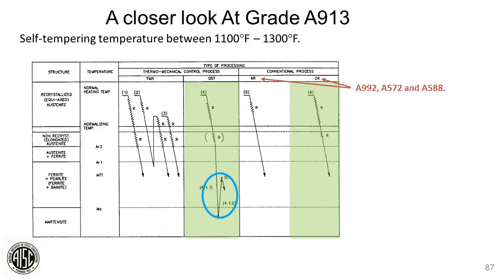If you can go to the next slide, we'll blow this graph up again. Here we go. This is the self-tempering temperature. In other words, we do all the control rolling, then the quench, that's this real steep line dropping down to below what we call the martensite start temperature. And then there's a self-tempering temperature. In order for the steel to be certified to A913, that self-tempering temperature, that rebound, has to be between 1100 and 1300 degrees. We go to the next slide, please.